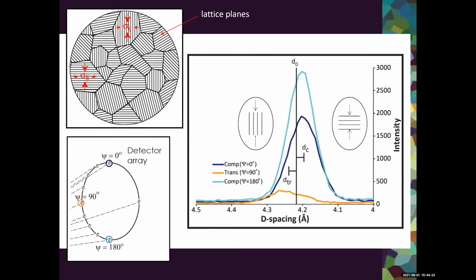So looking a little more into X-ray diffraction in a polycrystal, polycrystals, as I mentioned, have lattice planes that are diffracting. And as the diffraction peak shifts in response to the stress states of the groups of grains contributing to specific diffraction peaks, this gives us a way to look inside the polycrystal at what's occurring. So in an energy dispersive setting, we can have a plot like this where we have our intensity for our diffraction peak as a function of the d-spacing. And this is just showing that during uniaxial deformation, in the transverse direction, so diffraction that's collected from the detector at 90 degrees, the d-spacing is going to increase, while diffraction planes that are oriented normal to compression will shift to a smaller d-spacing.